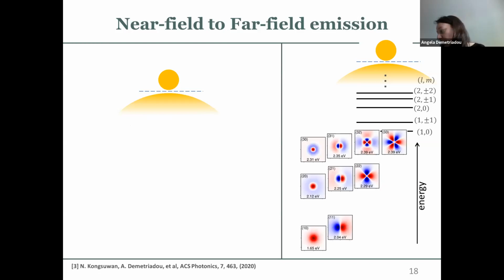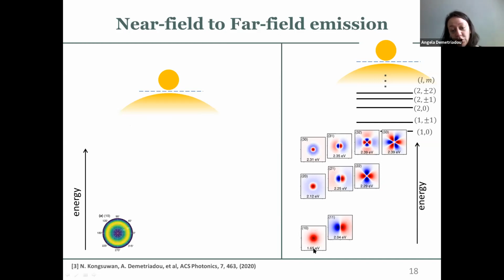So what I would like to talk briefly about afterwards is how does each of these modes that exist within this very small gap emit to the far field? What's the profile of the far field emission? So here I have again the same set of modes that I introduced before, sitting on an energy axis here, and the lowest order mode, which is the one that we usually consider, which is the 1,0 mode, emits in a conical way.